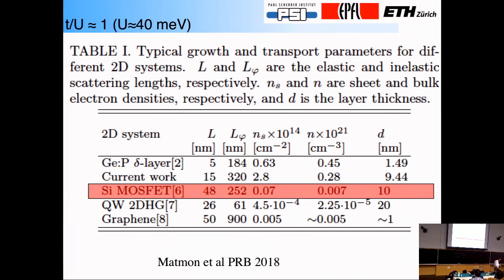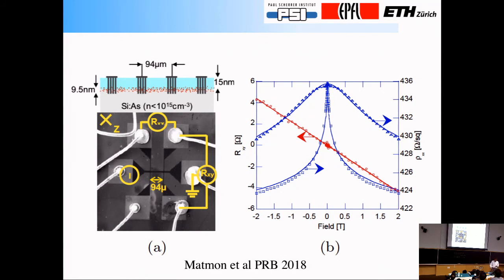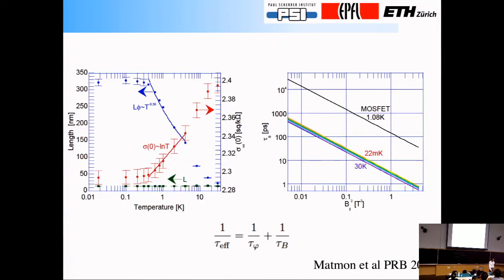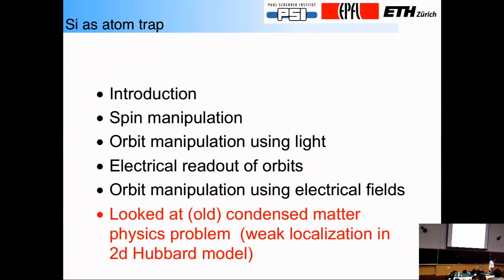But we're also here dealing with a phosphorus array, which really has a well-defined U at each site. We know where the U's are coming from. And in essence, what happens for this particular system is we have all of the usual transport data and everything else for the situation where T over U is very close to unity. And I'm not going to talk about all this data, but what's remarkable is that the known theory for essentially the disordered, basically two-dimensional Fermi liquid actually works perfectly when T over U is of order 1.